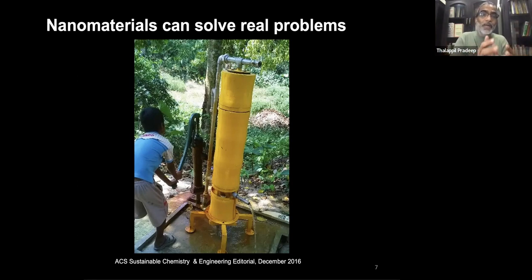Great. Now what happens when arsenic containing water is filtered? You have arsenic in this material. How do you dump it? In this kind of materials, we found that they don't release arsenic even after their useful life beyond a fixed concentration. So if this soil contains a certain amount of arsenic, the leach rate is below the concentration in this water region.